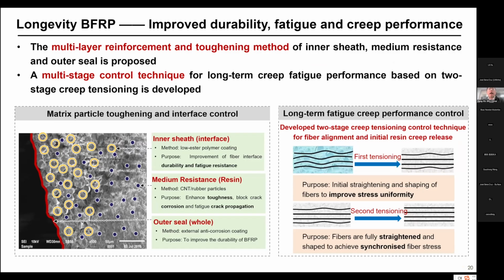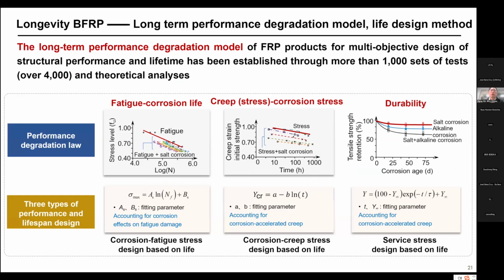Okay, for the durability enhancement for the basalt fiber composites, we propose a kind of method from 3 stages. One is from the surface of the fibers, and the second is from the resin modifications, and finally is outer shell for protection of the composites. And also considering the fatigue and creep performance, some pre-tension for the composite materials shows a very good ability to enhance the fatigue and the creep behavior. Okay, so with these efforts, we also propose some models to predict its long-term behavior.